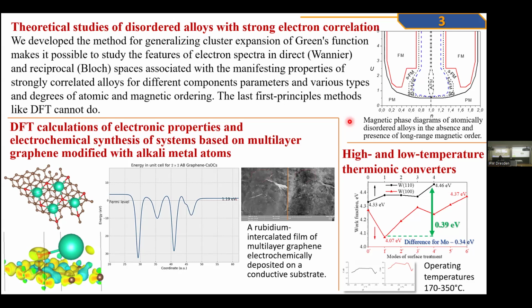They fill a vacuum gap between electrodes and are adsorbed on their surfaces. However, due to the high chemical activity of cesium, it is very difficult to retain it on the surface of the electrodes. Therefore, we search for a system that would allow binding cesium on the surface, in particular, a system based on multi-layered graphene.